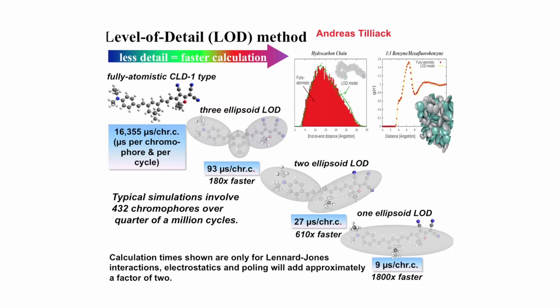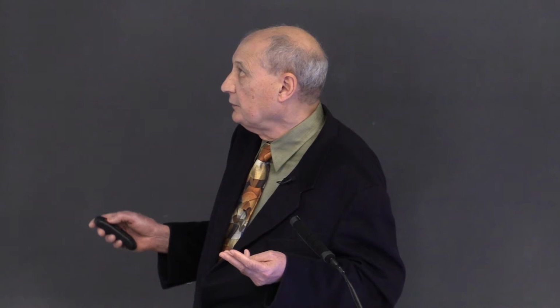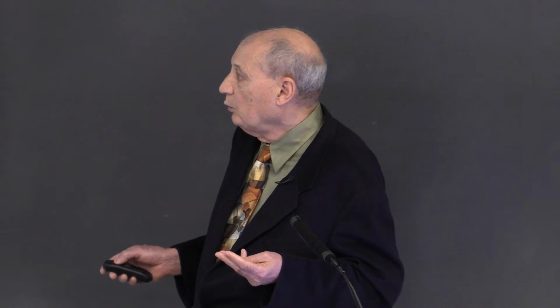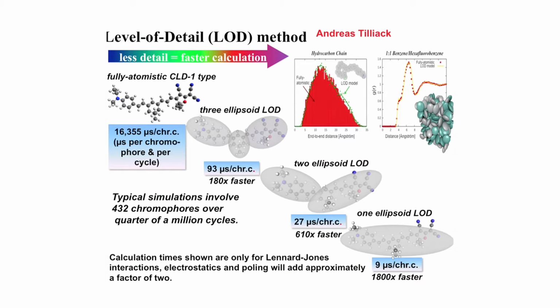In fact, they've done a very nice job of simulating the dielectric permittivity of dipolar liquids ranging from water to acetonitrile to other dipolar materials by using shaped objects for the united atom approximation. Another thing we just noted that Andreas did was to use different levels of detail as required. For example, a level of detail of 1 works fine if you're talking about low number density materials. But as you go to higher number density materials, you have to use a higher level of detail.